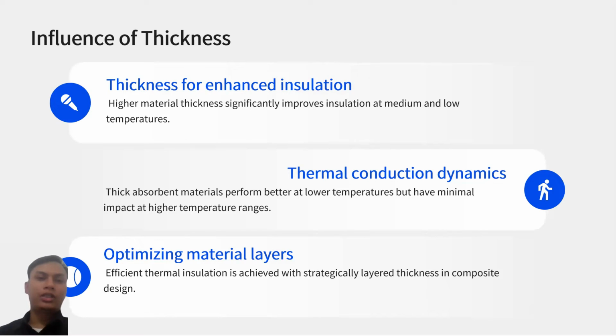Influence of thickness. A thickness enhances insulation. Higher material thickness significantly improves insulation at medium and low temperature. Thermal conduction dynamic. Thick absorbent material performs better at lower temperature but has minimal impact at higher temperature range. Optimizing material layers. Efficient thermal insulation is achieved with strategically layered thickness in composite design.